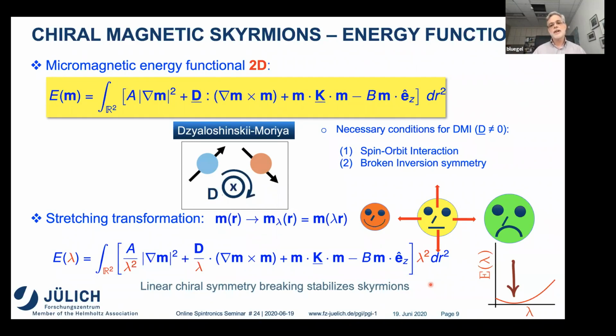And you also see a very important quantity is obviously this magnetic anisotropy, because the magnetic anisotropy is the quantity which wants to squeeze the skyrmion to death. And therefore, there is this very fine balance between the Dzyaloshinskii-Moriya interaction and the magnetic anisotropy. And this explains, for example, that the skyrmion phase diagram of a bulk sample and a sample which is grown by sputtering on a substrate can be quite different, because if you grow it on a substrate, you might introduce a small strain in your system. And this small strain changes the magnetic anisotropy, and this change of the magnetic anisotropy brings you in this skyrmion balance somewhere totally different. That is an important aspect.